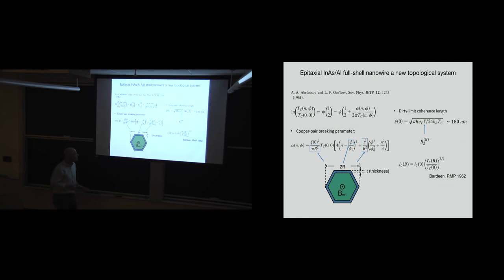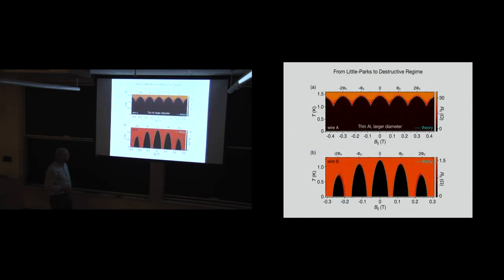And so we just plug all of that in, including what the critical current is, and lo and behold, that's Abrikosov-Gorkov theory just plotted with no free parameters. And so, good, that's great. Hadn't been done before, but this is what I wanted, because the last thing I wanted was for the shell to be interesting. So the shell is surprising, maybe, that it has these lobes and this destructive superconductivity, but it's 1961 physics. It's mean field theory, it works fine.